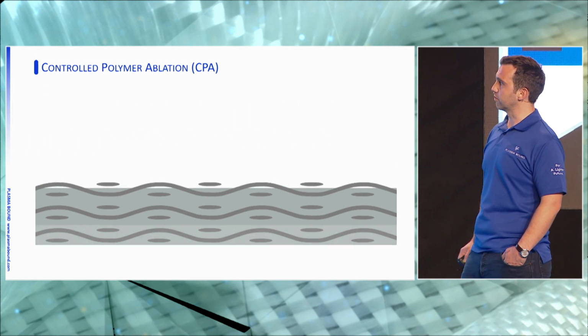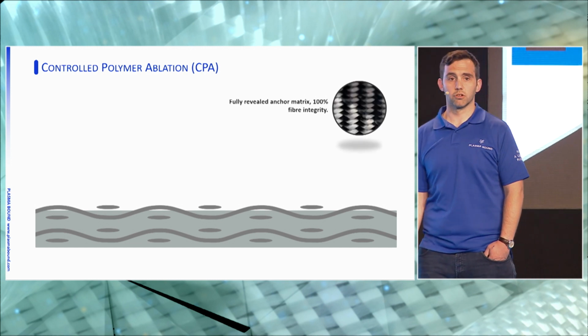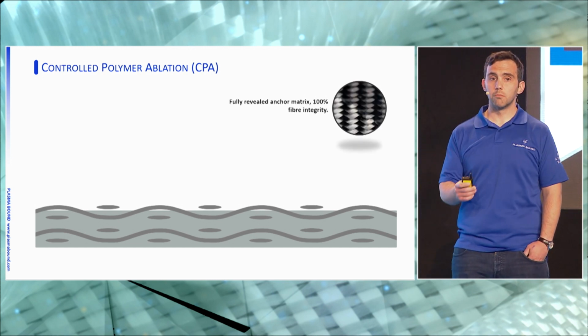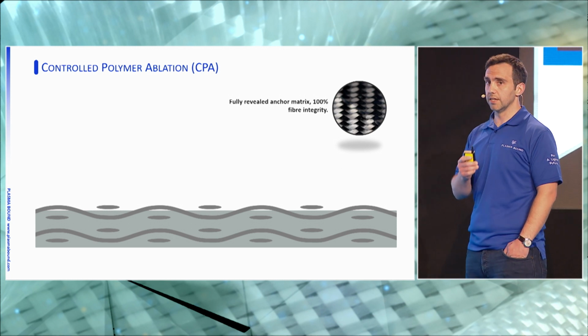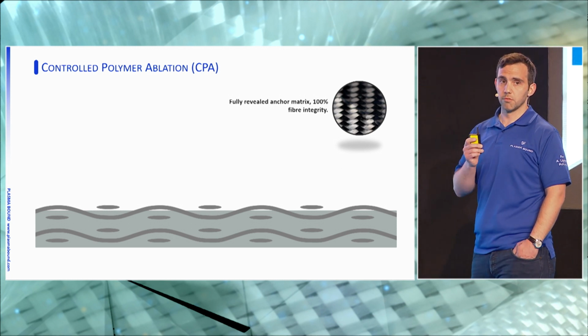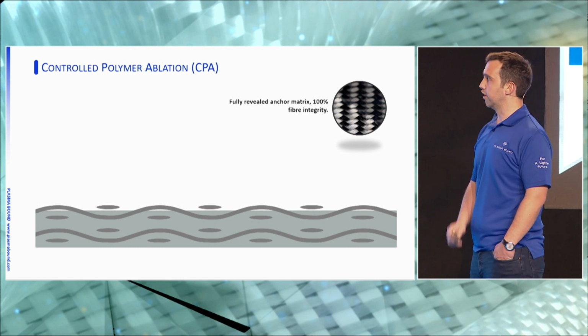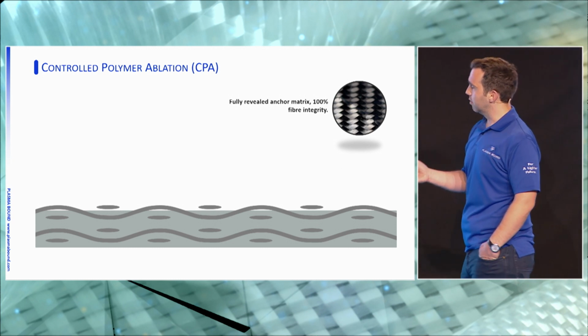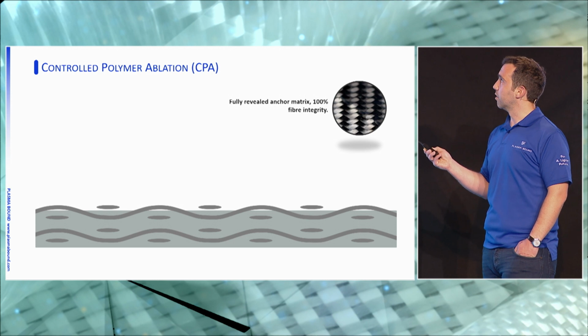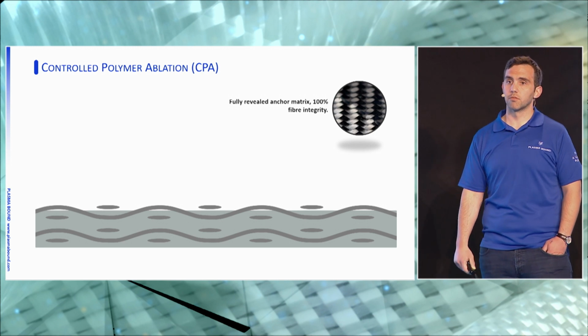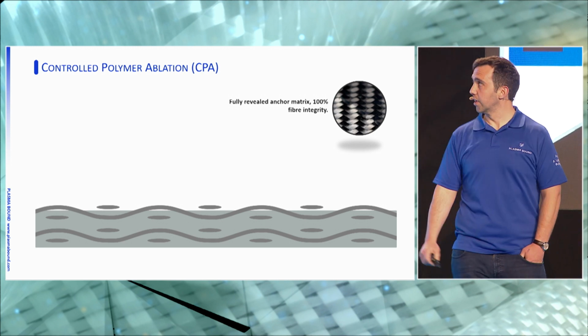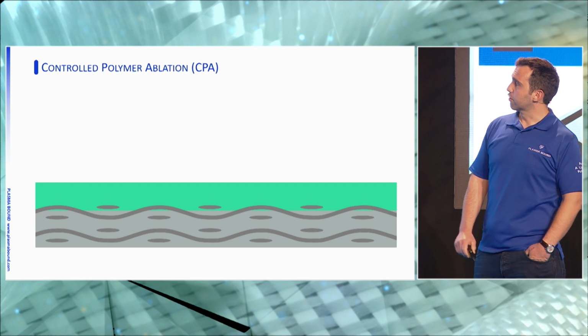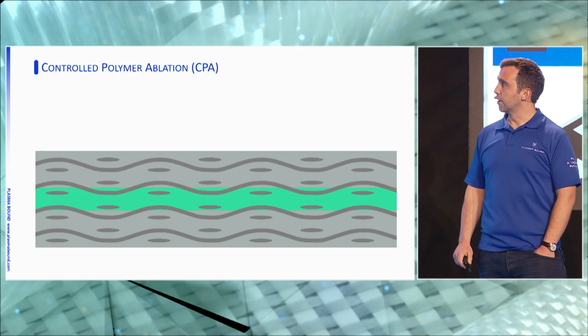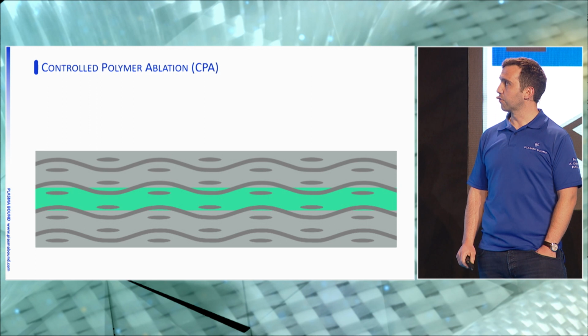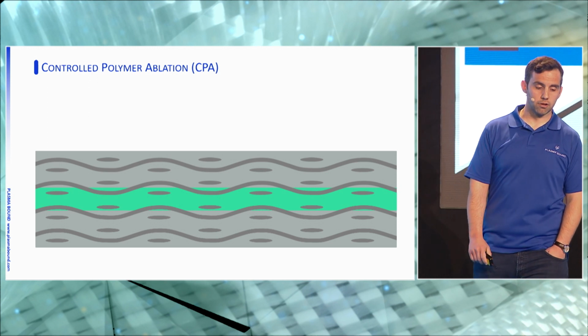And that's what CPA does. It removes the top layer of polymeric structure and exposes the fiber system to the amount that you, the customer, the client, wish. We can change that. We can trim it, skim it, fully reveal or partially reveal the fiber system. And on the top right here, you can see an example of an epoxy system where the epoxy is still present, and right beside it are exposed fibers, previously infused. When these are exposed, you can then induce your adhesive or place in your adhesive and then subsequently bond an adherend on the other side.